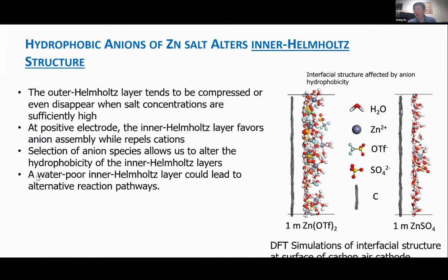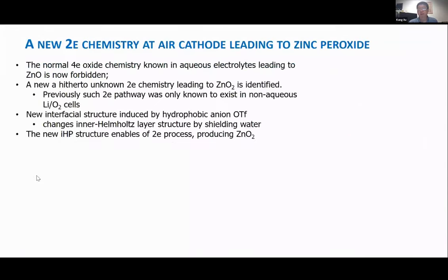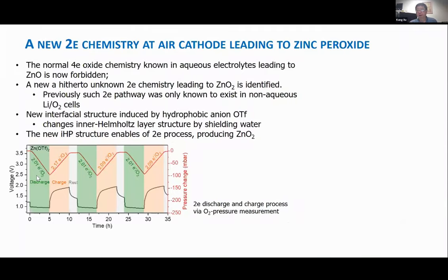We found that under positive polarization, the OTf strongly assembles there and it expels water from the inner Helmholtz layer, which is very unique because in this case, when we apply this to the air cathode chemistry, that's a simple carbon air cathode, we found the chemistry happening there is no longer the full four electron process of the oxygen reduction, but a very simple, very direct two electron process, which directly forms zinc peroxide. This has never been observed before in the aqueous system.